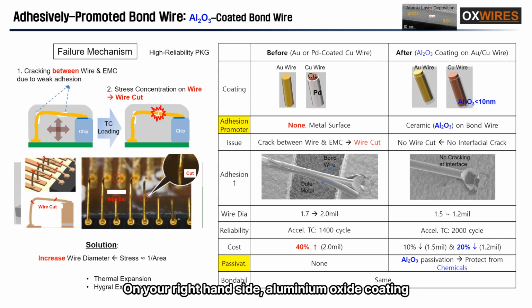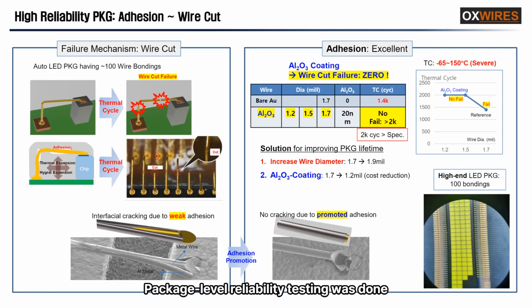On your right-hand side, aluminium oxide coating on conventional bond wires can provide adhesion promoter. So, aluminium oxide can prevent interfacial cracking or fracture between the wires and EMC. So, aluminium oxide coating can prevent wire cut failure. Package-level reliability testing was done for high-reliability packages susceptible to wire cut failure during accelerated thermal cycling.